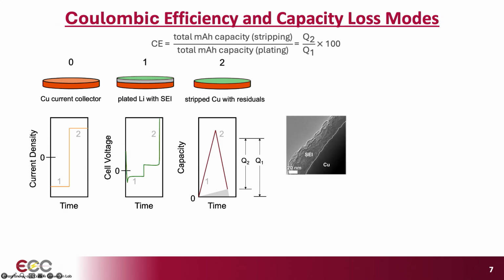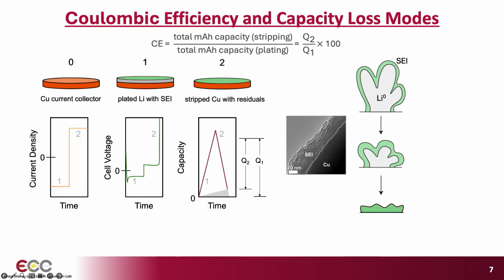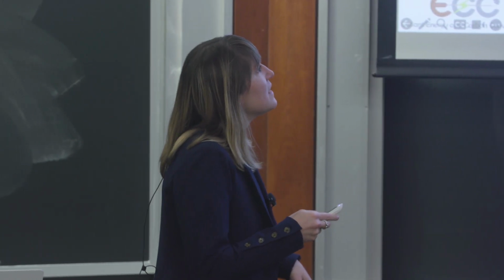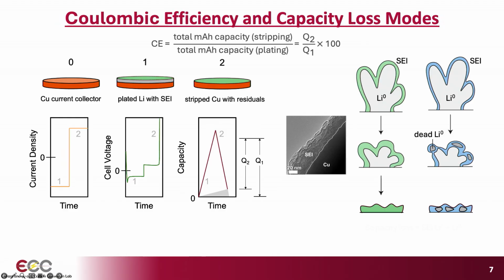So this is what the residuals on the copper current collector actually look like following a stripping process in a practical sample. And so in the ideal case, when we're stripping lithium, we're able to remove all of the metallic lithium, and all we're left with on the current collector is the SEI. So in this case, the Coulombic inefficiency is directly determined by how much of the SEI we had to form. Now, realistically, there's another capacity loss mode. What can happen is that the metallic lithium can become pinched off due to necking effects, and it can become stranded as metallic lithium within the SEI, so you don't recover it either. So in the most general case, the capacity loss is partitioned into two modes: ionic SEI lithium and metallic lithium.